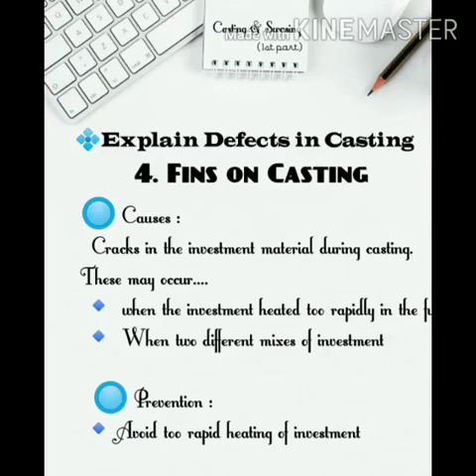4. Fins on casting. Causes: Cracks in the investment material during casting. These may occur: 1. When the investment is heated too rapidly in the furnace. 2. When two different mixes of investment are used. Prevention: Avoid too rapid heating of investment.